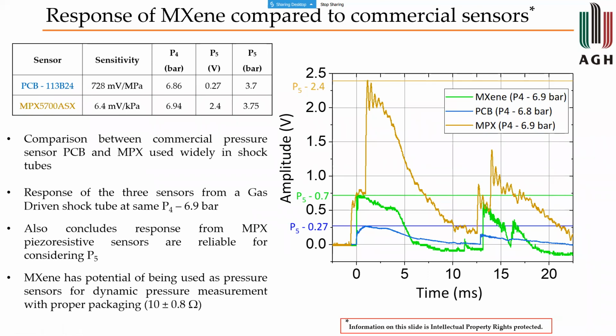And one of the outcomes from the studies that we made was that it was quite possible that there is some kind of piezoelectric or a flexoelectric effect with these samples of 2D materials, which is still under investigation that we've been doing for the last 1 year.